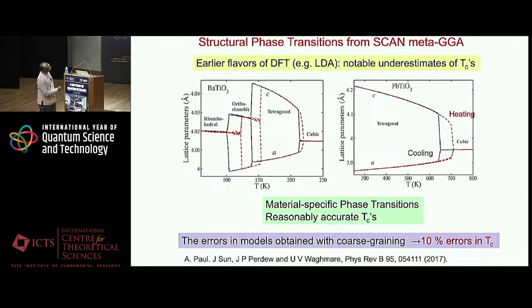Basically, we have used a recently developed DFT functional by John Perdew. This is called the strongly constrained, appropriately normed DFT functional, which satisfies 16 different sum rules, and which is known to be more accurate than the earlier flavors that we used, which grossly underestimated the transition temperatures. But with some of the new advances in DFT, now we can predict Tcs even with this modeling within 10% of the experimental Tcs.